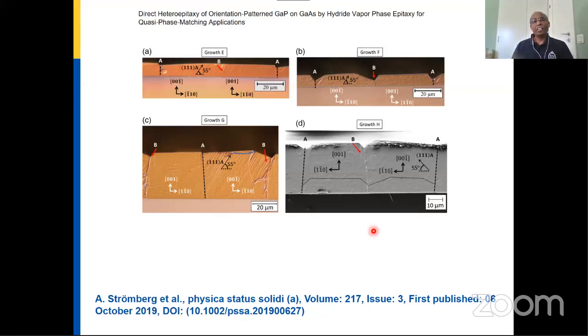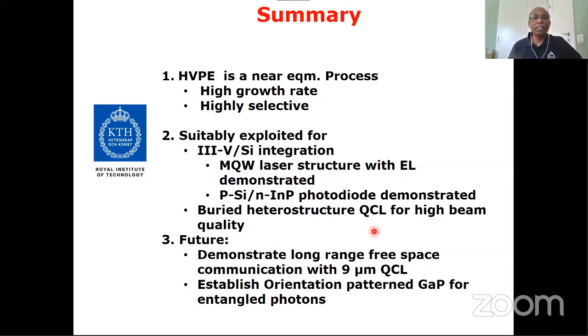Okay, I think that's all I wanted to say. So I just want to summarize. HVPE is a near equilibrium process. It has a high growth rate and high selectivity, and is suitably exploited for III-V silicon integration. And I've shown you a multi-quantum well laser structure with electroluminescence demonstrated, a P-Si/n-InP photodiode demonstrated, and different types of buried heterostructure QCLs for high beam quality.